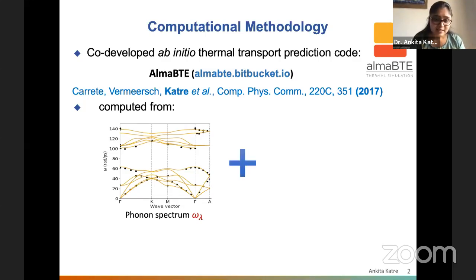The thermal conductivity, which is represented with the Greek symbol kappa, is calculated from two main ingredients in this ALMA-BTE code. The first is the phonon dispersion. As I said, it sums up the contributions of each and every phonon mode, so we need information on the harmonic vibrations, the normal modes, which are basically the quanta of the heat energy.